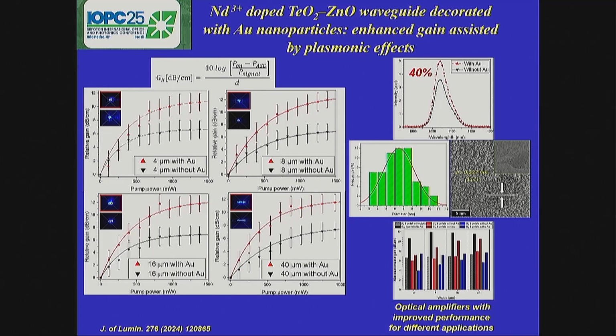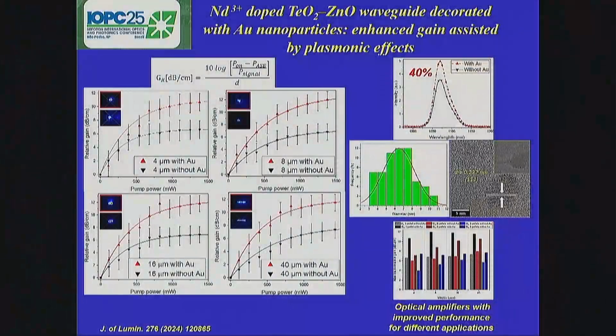We performed the transmission electron microscopy measurements to evaluate these gold nanoparticles. In the figure, I show you the size distribution. We have many particles with diameters around 6 and 7 nanometers. This is an image in which I show you an isolated spherical particle. This is not clear, but this interplanar distance corresponds to the crystalline planes of gold, corroborating the presence of gold nanoparticles in crystalline form.